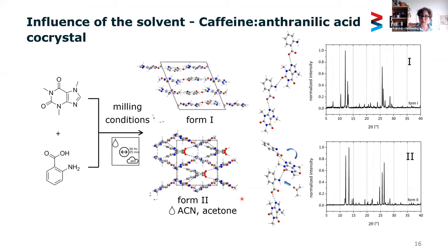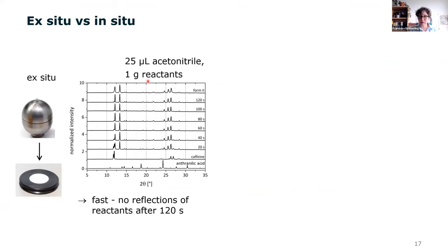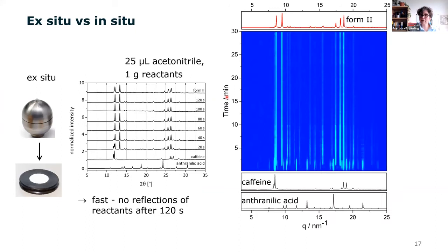We were also interested in whether we only need really tiny amounts of material. And here you see ex situ data for 1 gram of reactants and 25 microliters of acetonitrile. And you can see that the reaction really moves on very fast after 120 seconds. So always stopping the reaction and then measuring the product, we cannot see any traces of the reactants. And this is more or less the same reaction done in an in situ setup. And you can see what we measured here ex situ, luckily, is the same thing we also observed under in situ conditions. It's a fast transformation. That can be the case, but not all the time. And I will show you some examples.